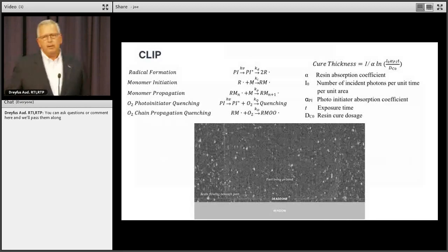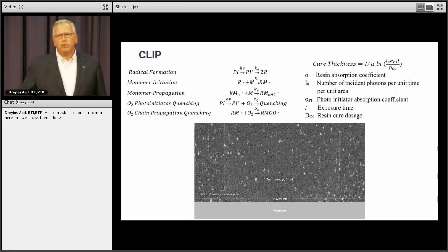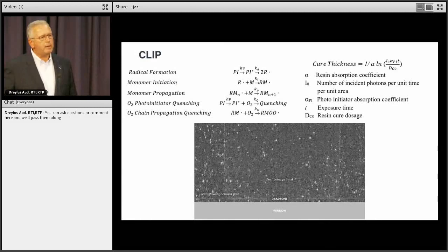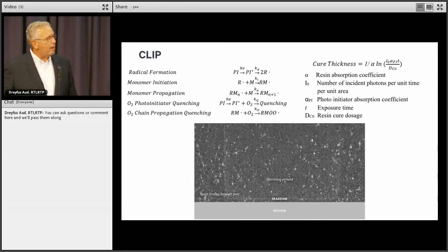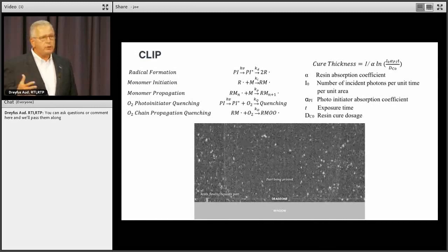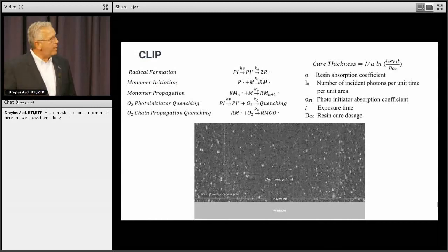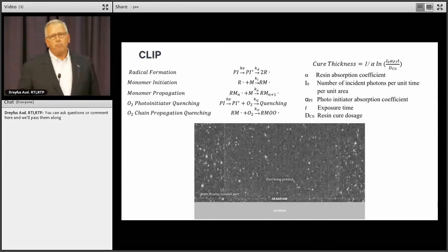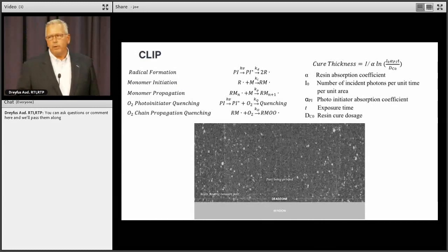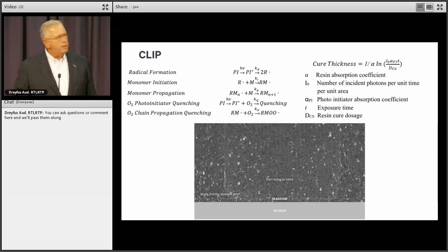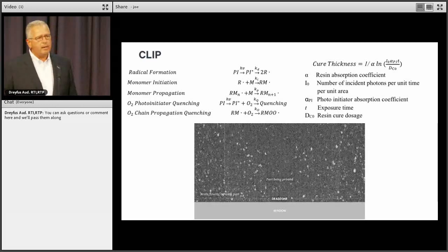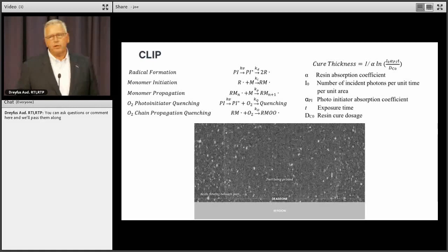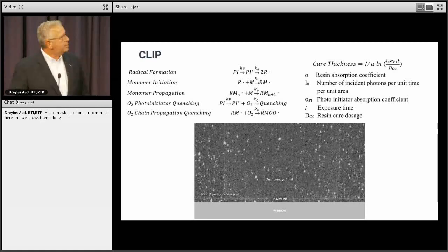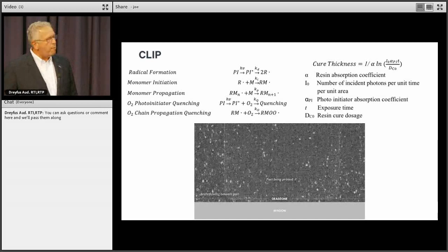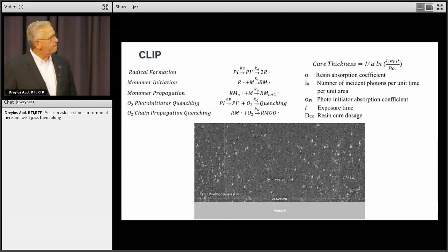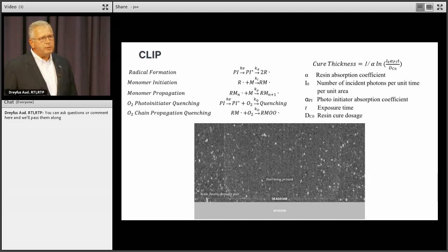And so this image here, this is optical coherence tomography. Think of it as ultrasound imaging with light instead of sound waves. It's a cross-section of us growing a part. Right in the center is a 2 millimeter diameter part growing at 200 millimeters an hour. The speckles are nanoparticles that we doped into the resin as a contrast agent. And so what you see is this part growing right off the base of the window, where the light is the most intense right in the center.